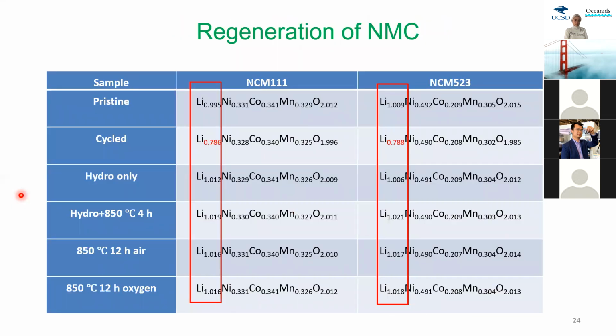Okay, so in terms of the chemistry, if you do not want to focus too much in terms of all the metals, and you just have to focus on the lithium composition, which I have boxed them. For both chemistry, both materials, I use them as an example, NCM 111, NCM 523. So this is pristine. You can imagine pristine means the batteries that you just buy, okay? You buy a fresh cell phone, you have a fresh battery, then they will have about 100%, which is 1.0, something like this is very close, 0.995 or 1.009. This means basically is 100% of lithium.